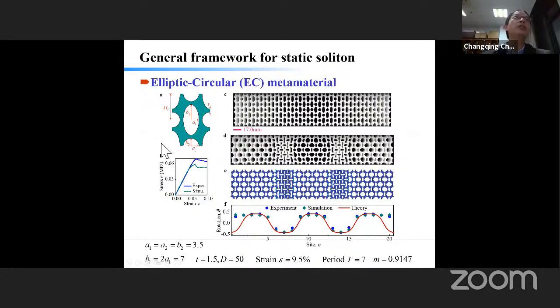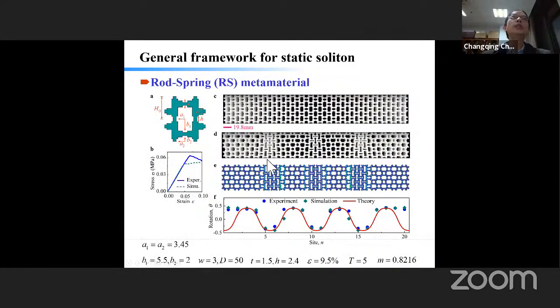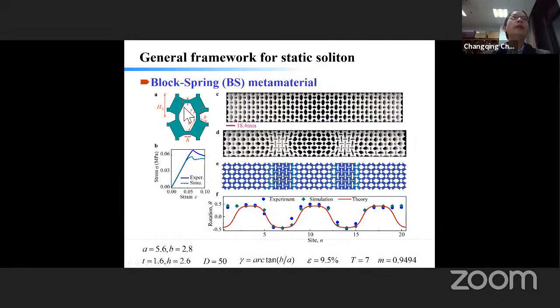And we also designed square holes, and we have a uniformly distributed localized deformation zone. So basically it means, following the general framework, we are able to get a static soliton, which is independent of the shape. We have defined different metamaterials. Here, basically, it's one-dimensional, because you can see the deformation pattern is independent of y in the vertical direction.